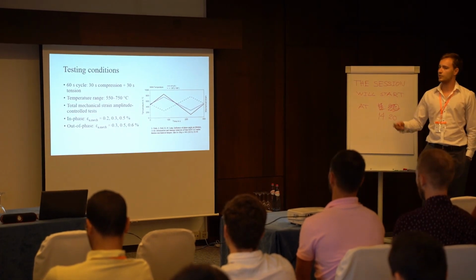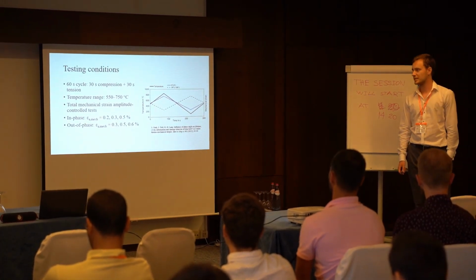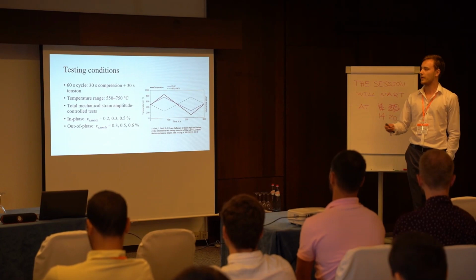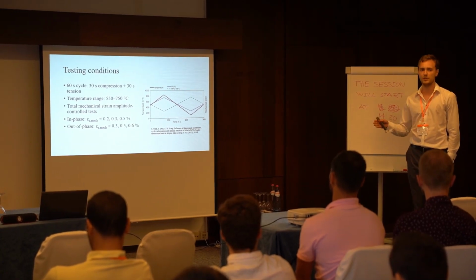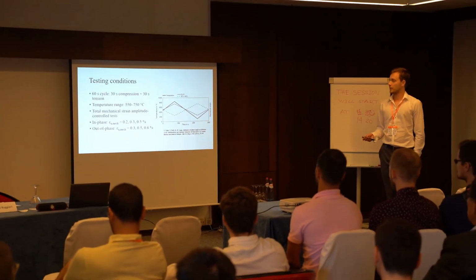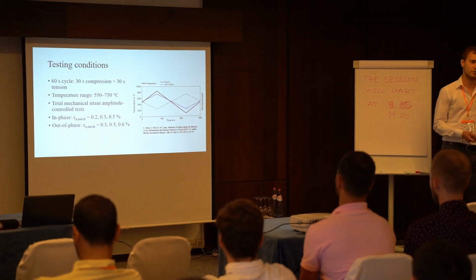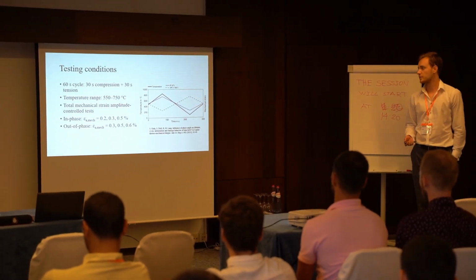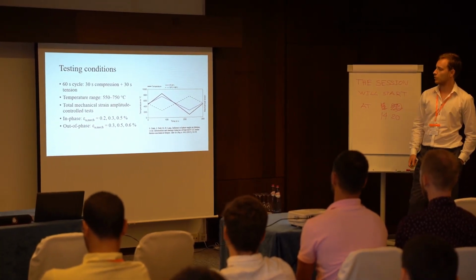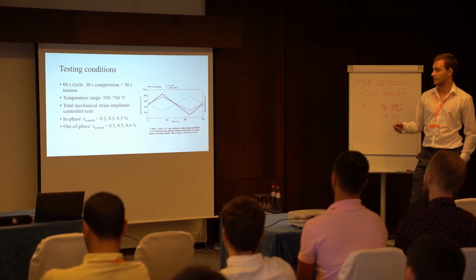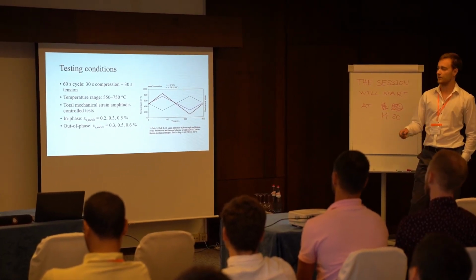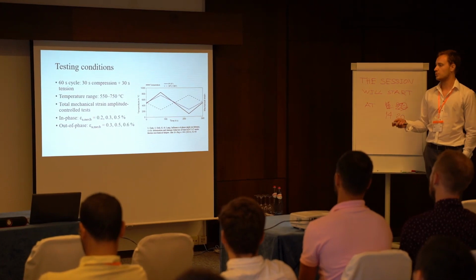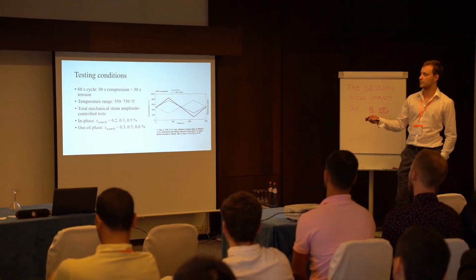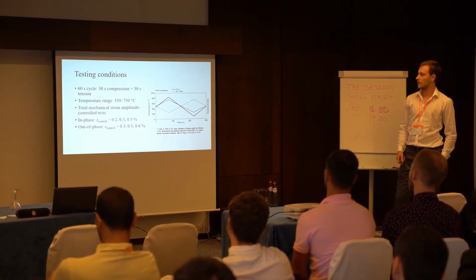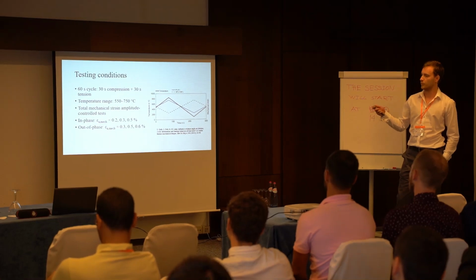So regarding the testing conditions, the cycle time was 60 seconds, which means we had 30 seconds of compression and 30 seconds of tension per half cycle. We tested the specimens in the range of 550 to 750 degrees centigrade, and the tests were controlled with mechanical strain, total mechanical strain amplitude. In case of in-phase tests, the strain amplitudes were 0.2, 0.3, 0.5%. In case of out-of-phase tests, it was 0.3, 0.5, 0.6.